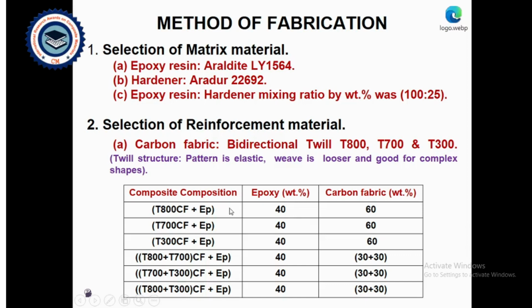The composite compositions studied were T800 carbon fiber alone with epoxy, T700 alone, T300 alone, then T800 and T700, T700 and T300, T800 and T300 with epoxy. These are combined composites. The carbon fiber and epoxy weight percentages remain the same, 60% and 40% respectively. When it comes to an individual carbon fiber, it is 60%. When it comes to a combination, we selected 30% plus 30% for each of the two carbon fibers.